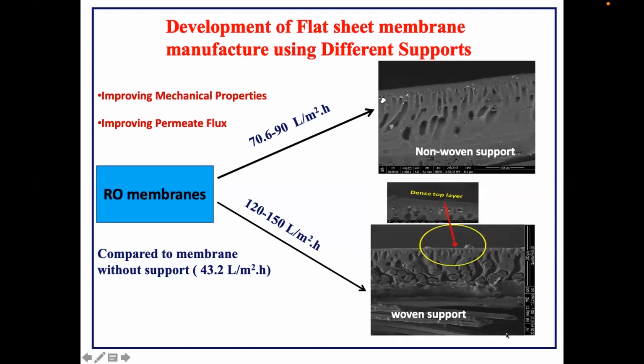For RO, normally we use it without support, and with non-woven and woven. We reached the same conclusion as in ultrafiltration, also in the reverse osmosis membrane: RO with woven support gives us a flux of almost 140 LMH. This is the best flux we get, and we compared it with the international limits. It is a good value, almost equal to the international limit.